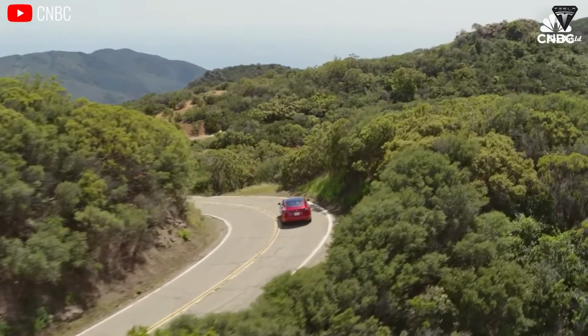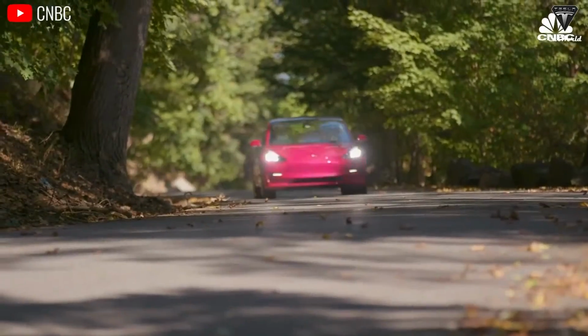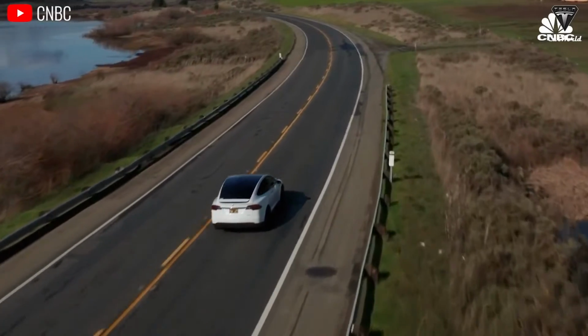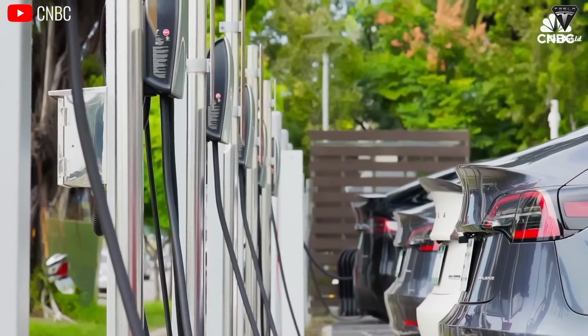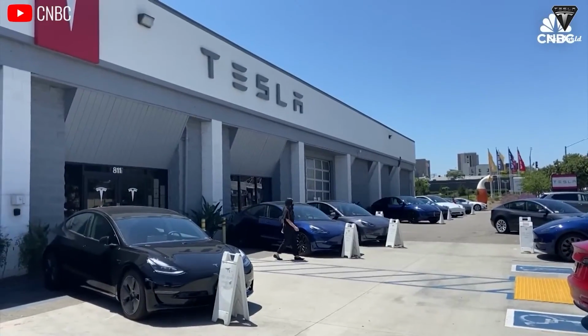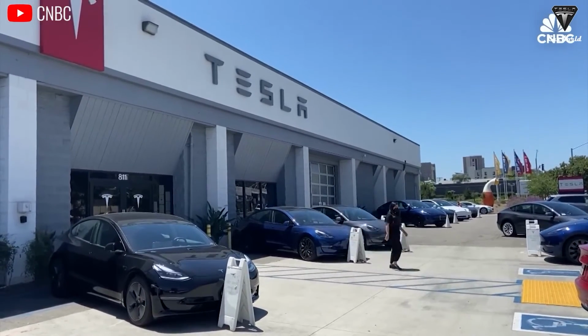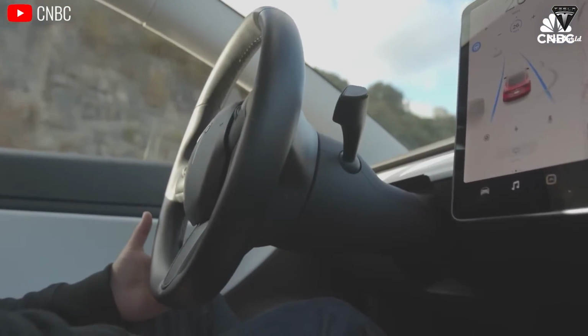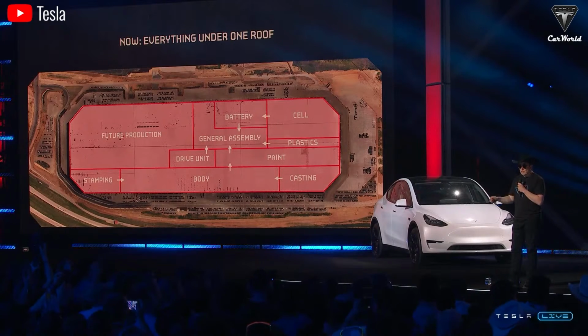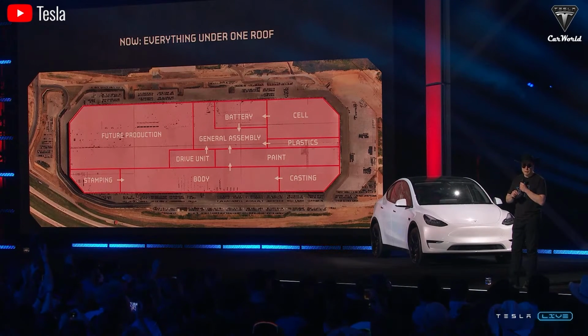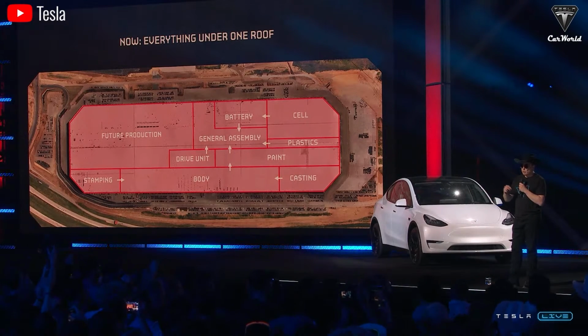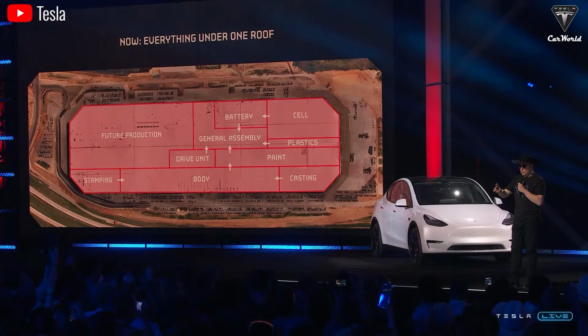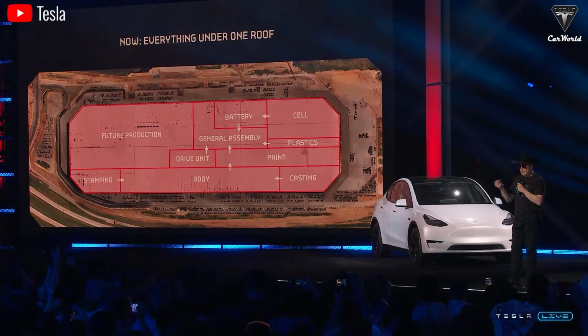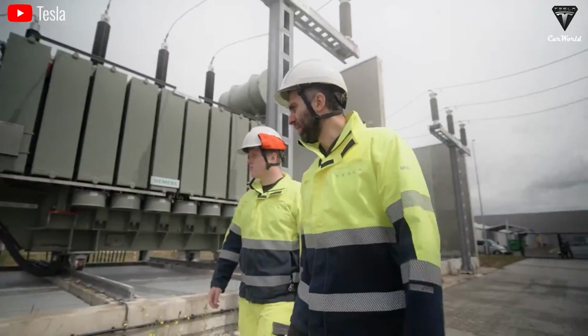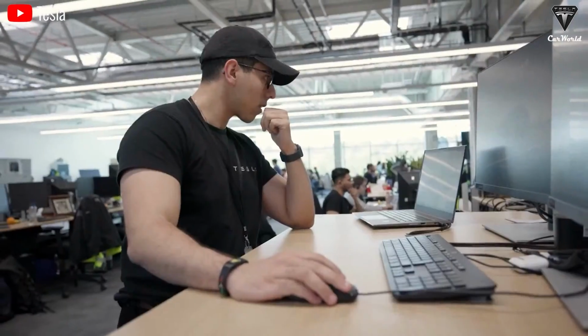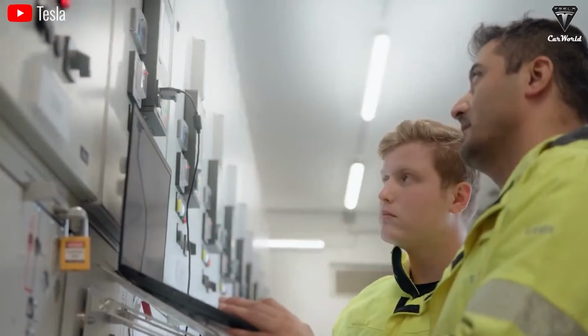50 cycles, that's still nowhere near enough for electric vehicles, as it would represent about 12,000 miles of driving. That said, 94% capacity retention at 50 cycles is still a good sign, as degradation often slows down, and therefore the battery could still have decent retention at much higher cycles. Back in 2022, Elon said in regard to manganese: manganese is an alternative to iron and phosphorus for scaling cathode production to several terawatt-hours a year. Manganese also requires less lithium, and it operates at a higher voltage. However, as far as we know, manganese batteries lose capacity faster, and researchers are trying to make them more durable.